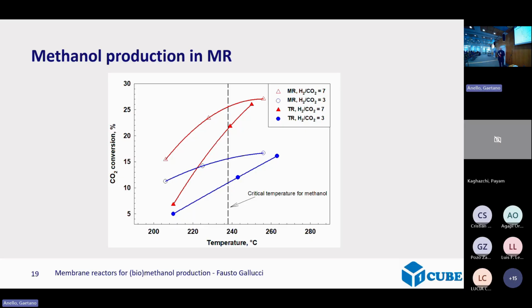What is not shown in this presentation, and I connect to the panel discussions, is that to get these results, I got 98 membranes, of which 3 membranes were water selective, of which 1 broke when I tried to put the catalyst inside. So we had only 2 membranes that were working properly. And Hannes is smiling because after my master, I went for some time to Germany. And there was a very nice young Hannes, he's also nice now, by the way, that showed how to produce zeolite membranes. And he produced a very nice zeolite membrane that again was not water selective at the end.